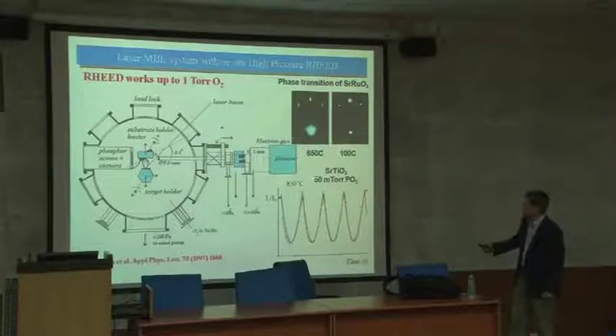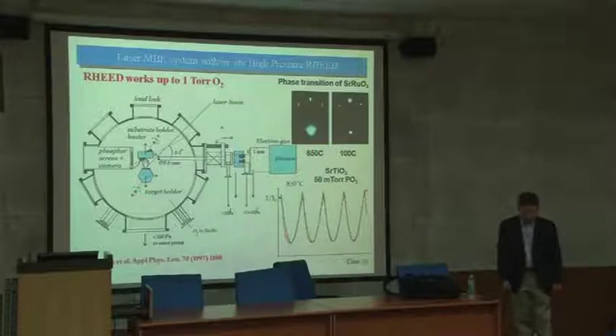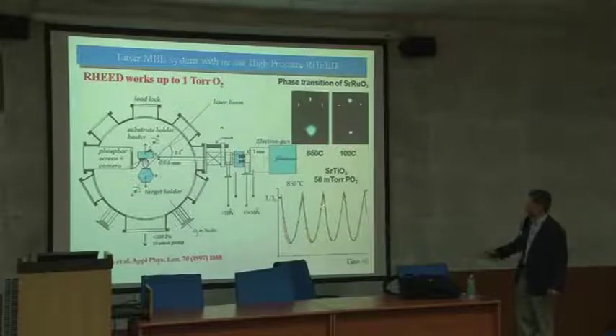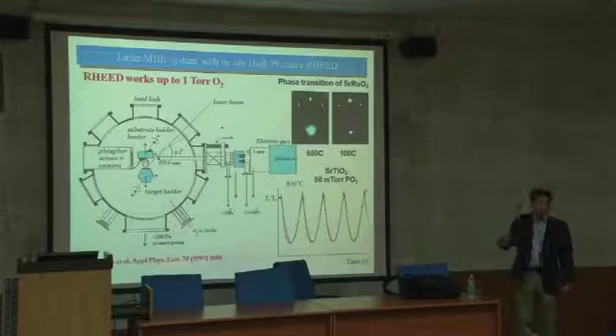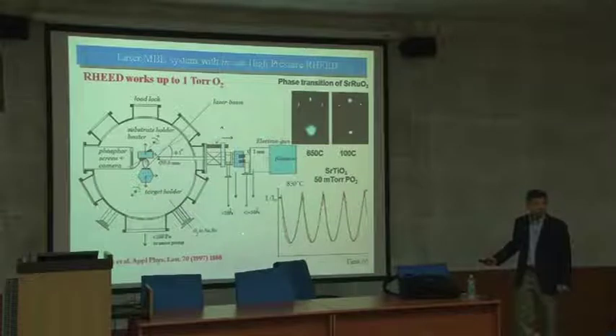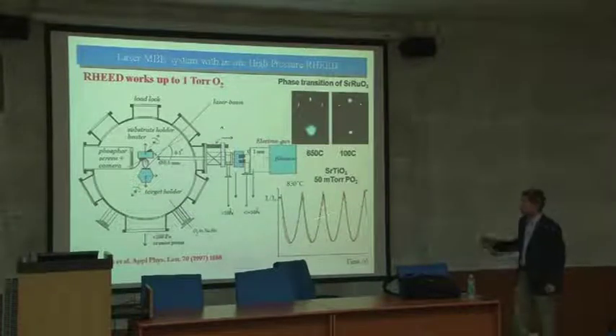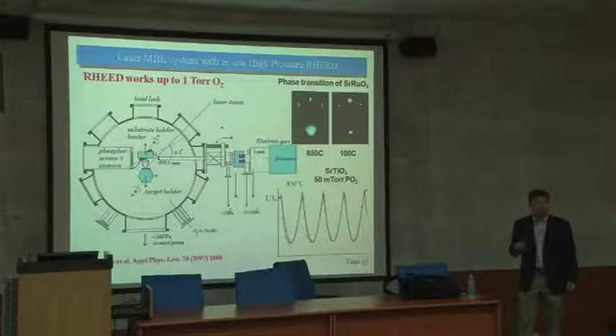And this is done at 50 millitorr of oxygen partial pressure, growth of strontium titanate. You can see that very nice oscillation. Okay, this is real data. When you grow this, you see the oscillation, which means this one 4 angstrom, another 4 angstrom, you have one layer, another layer, and that is possible by this method of RHEED.